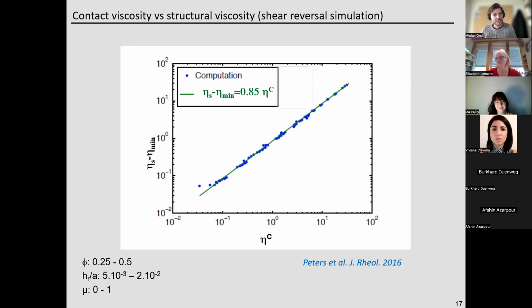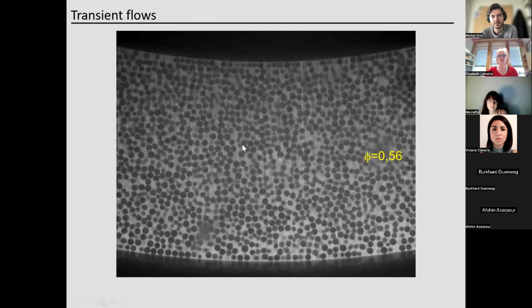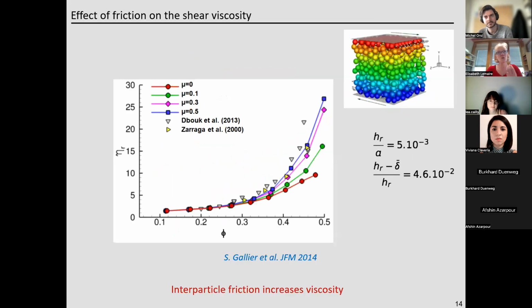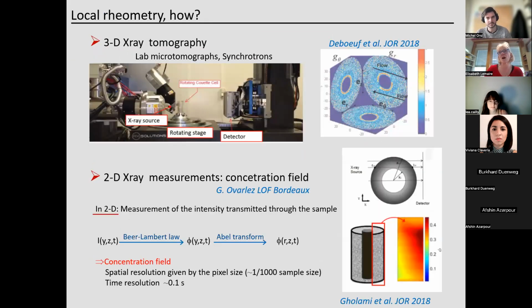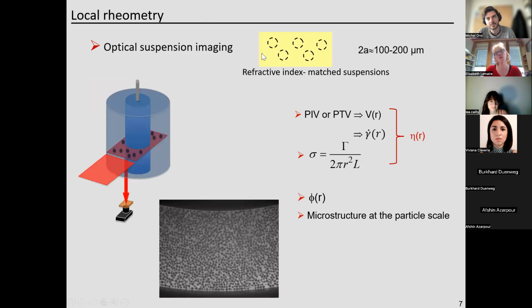I'm sorry. We also have a third question that came up: how do you deal with sedimentation with the local rheology measurements that you perform in your lab? Sedimentation? We do not have sedimentation because we use a density-matched suspension. And that's also why it's so difficult to find good suspensions to make a local rheometry experiment, because we have to match both the refractive index and the density. But we manage.